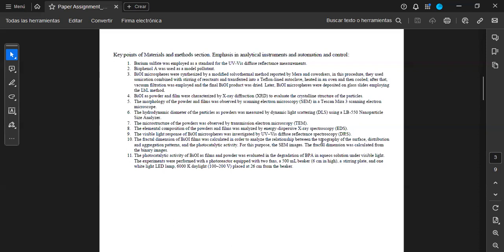Then, as the key points of the materials and methods section, we must emphasize the analytical instruments and automation and control. So for this study, barium sulfate was employed as a standard for the UV-Vis diffuse reflectance measurements. Then we have that bisphenol A was used as a model pollutant. Then we have that the BiOI microspheres were synthesized by a modified solvothermal method.